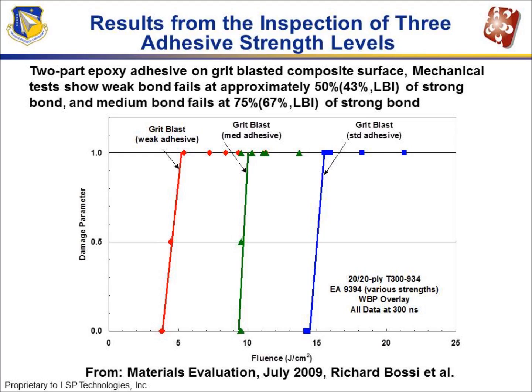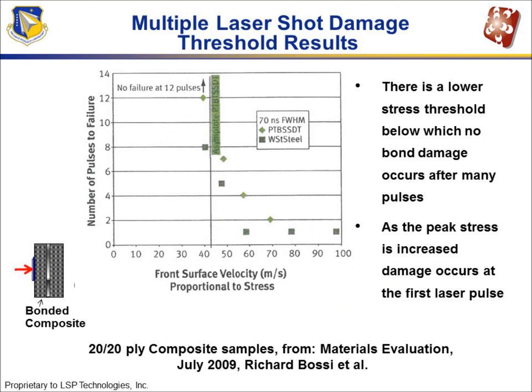This graph shows you the effect that multiple shots have on a bond line. It's important to understand that if you interrogate these materials and you are doing damage to it that weakens the structure, then you're imparting damage. And so we wanted to avoid that and know how the structure behaves with multiple shots to see if indeed we are interfering with the strength of the bond line. A test sample is represented here.